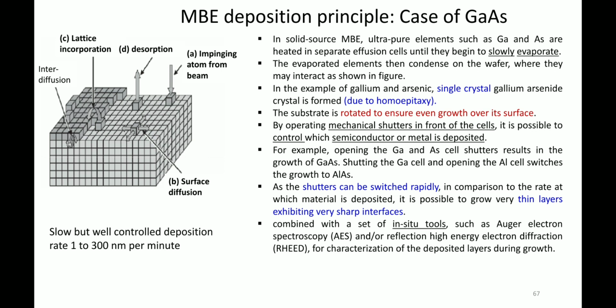So basically it helps you to understand how many layers of gallium arsenide have been deposited, a monolayer or 2 layers or 3 layers or 4 layers, atomic layers that are going to be deposited. And once the 5 nanometer is completed, then immediately your shutter for gallium gets closed and the shutter for aluminum is open, and then the system repeats. So these are the ways where, during the deposition, you can get high quality thin films of different heterostructures.